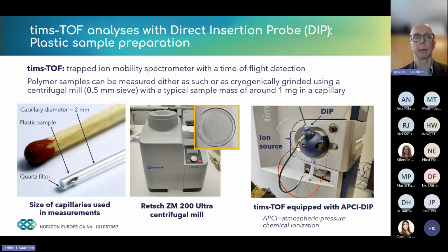So here is an example of the plastic sample preparation. On the left-hand side, you see a typical glass capillary that is used for doing the analytics. As we can see, we can work with a very small amount of material; typically around 1 milligram is sufficient. We can either take it straight from the plastics, or in the center, we have the cryogenic grinding using the Retsch ultracentrifugal mill with sieves, so that we can have the 0.5 millimeter sieve for these samples. Then these plastic samples, embedded into the glass capillaries, are put into the direct insertion probe into the timsTOF device, and we run these analytics in the atmospheric pressure chemical ionization mode.